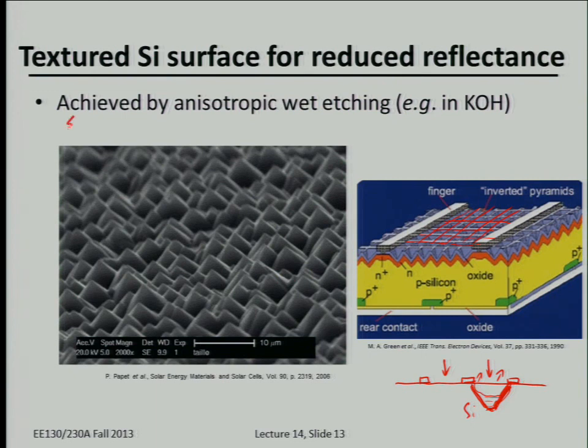Okay, so specifically, the 111 planes etch much more slowly, like more than 100 times more slowly, than the 100 and 110 planes. So this is due to something. What do you think it's due to?